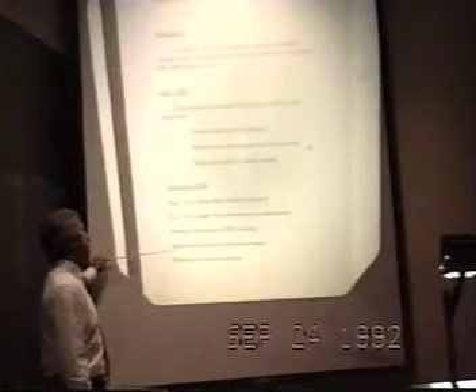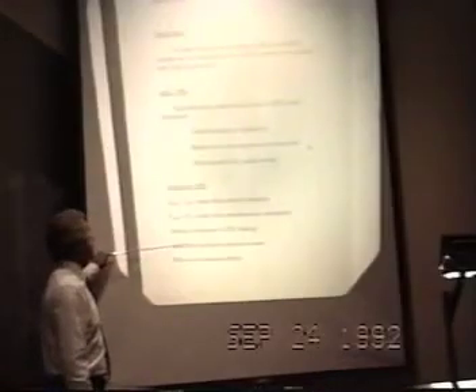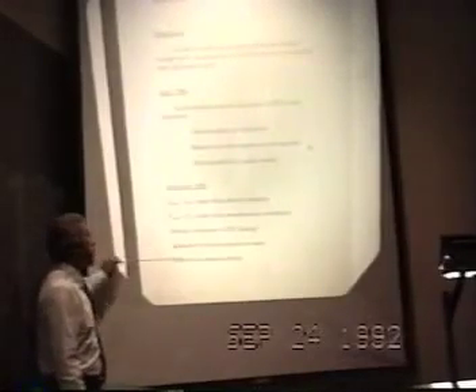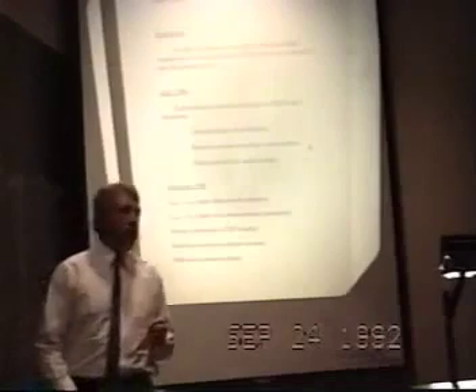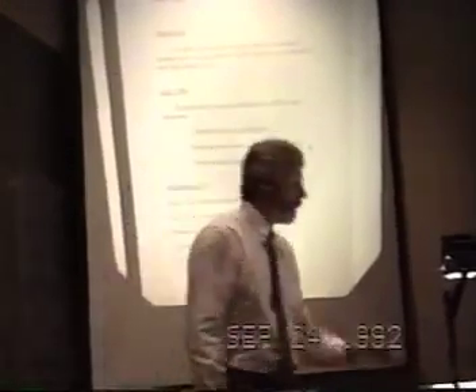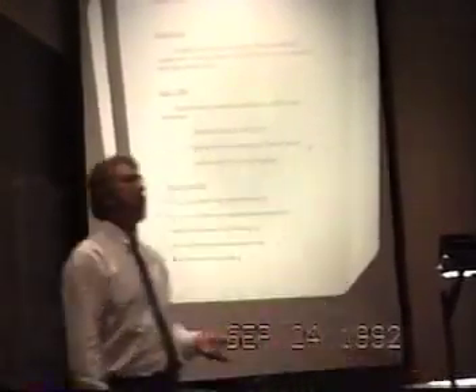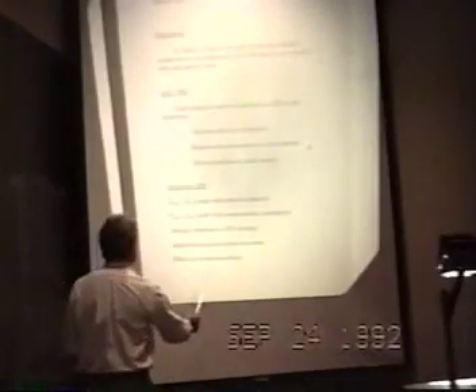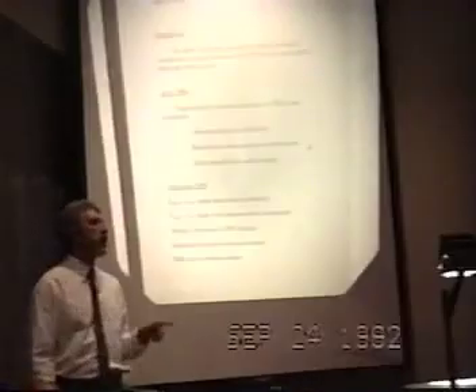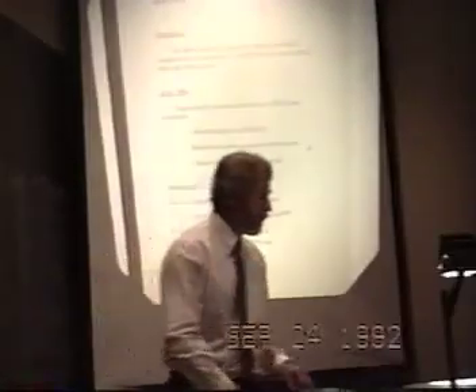We do not see, have not seen, quantitative nuclear products. And the condition that we're at now in our understanding of this anomaly is that the effect is either real or it's some obscure artifact, and perhaps an artifact that must change from experiment to experiment. The observations that we make are larger by at least 2 orders of magnitude than the known chemistry of the contents of the electrochemical cells.